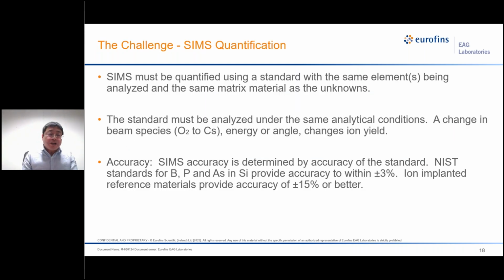So SIMS do have challenges. For quantification, SIMS must be quantified using a standard with the same elements being analyzed under the same matrix material. The standard must be analyzed under the same analytical conditions. Any change in the primary beam from cesium to oxygen, oxygen to cesium, or energy, or impact angle, all this will change the ion yield. So the SIMS accuracy is determined by the accuracy of the standard.